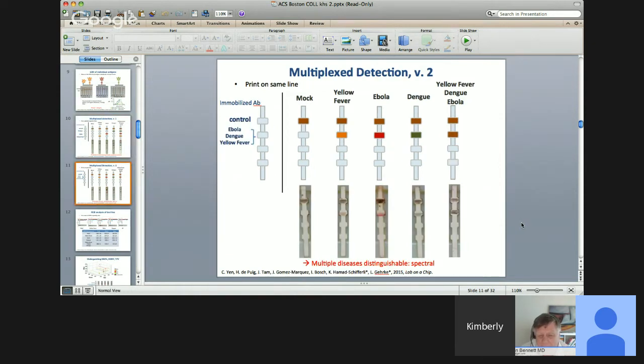Okay, so then what we try to do is to make it harder and actually co-localize all those antibodies for the test right here onto one pad. So basically, all the antibodies for Ebola and dengue and yellow fever are all in this position. And so we should only get a hit at that test line only. And depending on what is run through, if the biomarker for yellow fever is present, it should be yellow. If it's Ebola, it should be red. If it's dengue, it should be green. And if it's all three, it should be brown. Okay, and again, for mock, we should have nothing there.